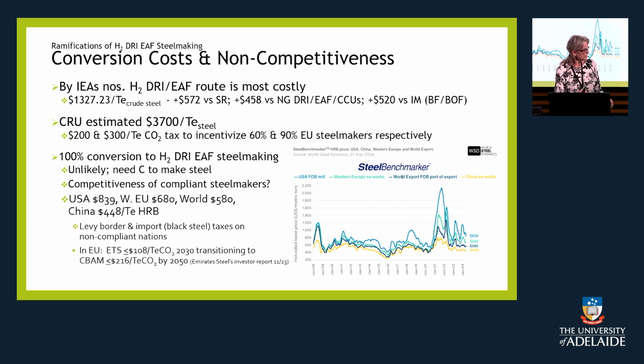The IEA numbers that were put out in 2015 through 2018, I calculated at $1,327 per ton of liquid crude steel. That's much higher than any of the other operations they put out, from smelt reduction through to the blast furnace BOF. The CRU in Europe actually calculated $3,700 per ton of steel. They said that a $300 per ton carbon tax would be needed to incentivize 90% of the European steelmakers to convert.